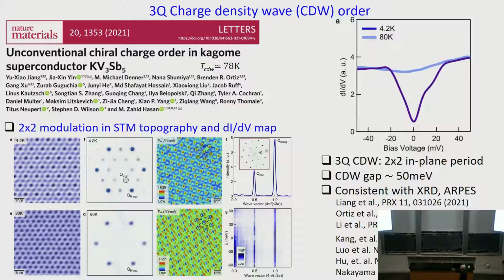And you look at the dI/dV as a function of bias, you see this is above the CDW transition. And when you go below the CDW transition, there is a CDW gap on the order of 50 meV that opens up. Great consistency between scattering experiments and ARPES experiment. Right? 3Q, 2 by 2 in-plane period. I should say there is actually an ordering wave vector in the third direction as well. It's 2 by 2 by 2. And Vesna has done NMR recently to give a microscopic picture of what the CDW phase looks like. I'll comment on that later.